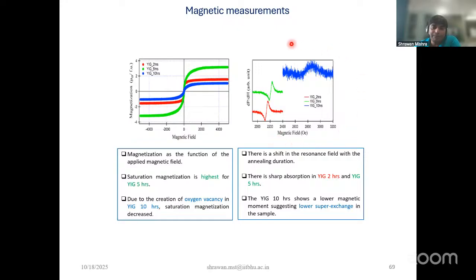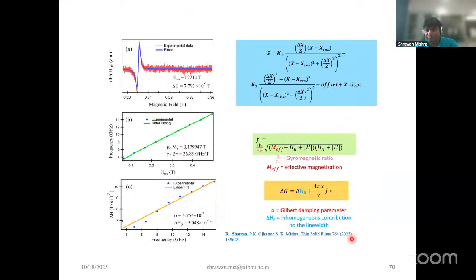Not only that, we apply FMR, and you can see the resonance characteristic coming into the field. So that means the garnet that we have prepared in our lab is well behaved. Not only that, we apply the LLG equation and Kittel fitting to find out the damping parameter as well as the effective magnetization. That's what has been seen here. So the alpha value that we are getting is 4.754 times 10 to the power minus 3.